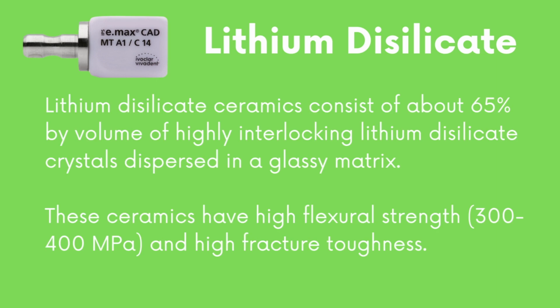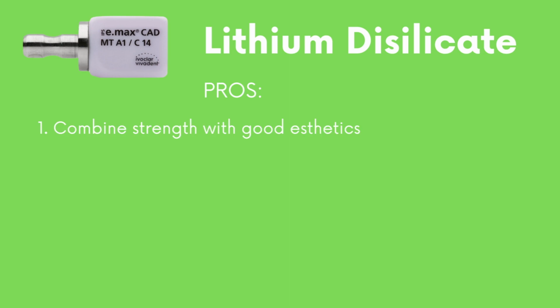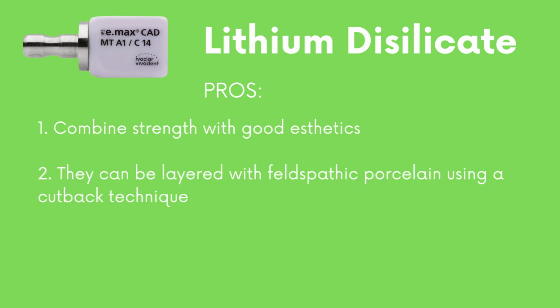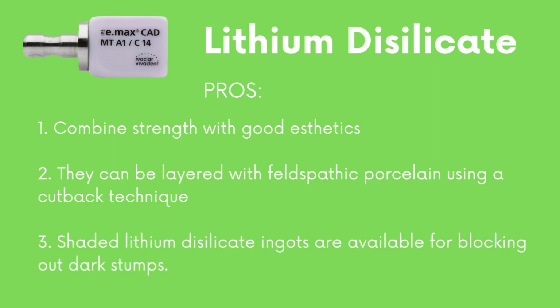Lithium disilicate ceramics consist of about 65% by volume of highly interlocking lithium disilicate crystals dispersed in the glassy matrix. These ceramics have a high flexural strength compared to the leucite-reinforced ceramic. Lithium disilicate restorations combine strength with good aesthetics. They can be layered with feldspathic porcelain using the cutback technique, and the shaded ingots of lithium disilicate are available for blocking out darker stumps. That's all well and good, but I think we should probably break down the fundamentals, because we love fundamentals here, of what glass-based silica ceramics consist of.